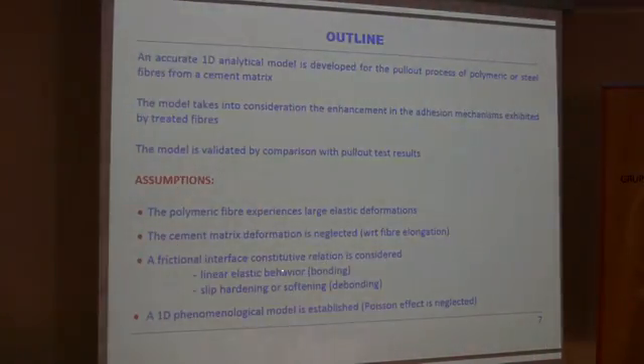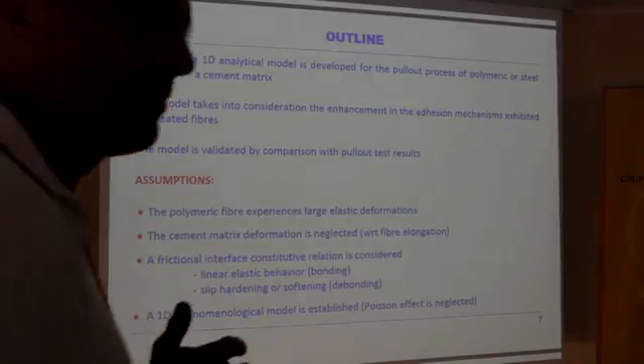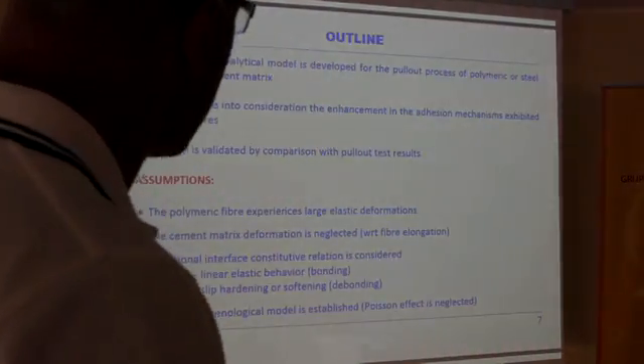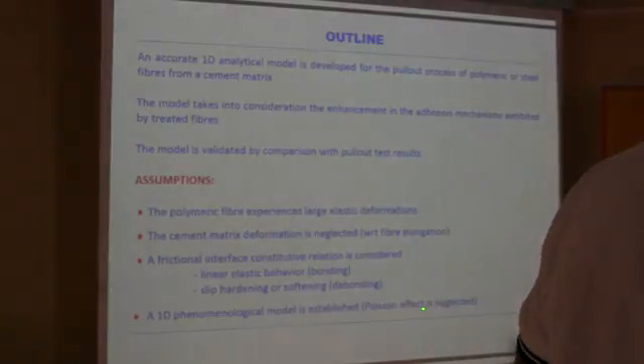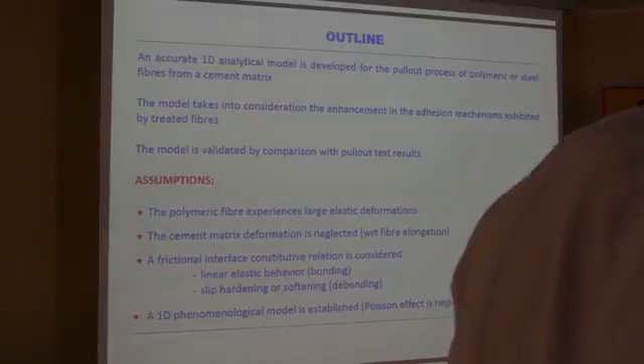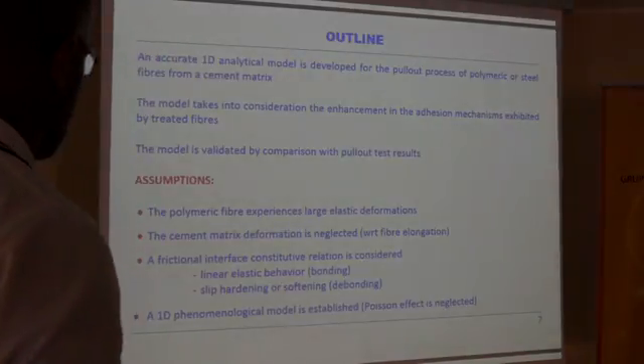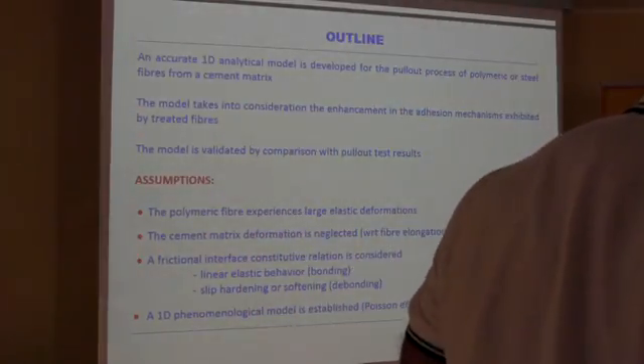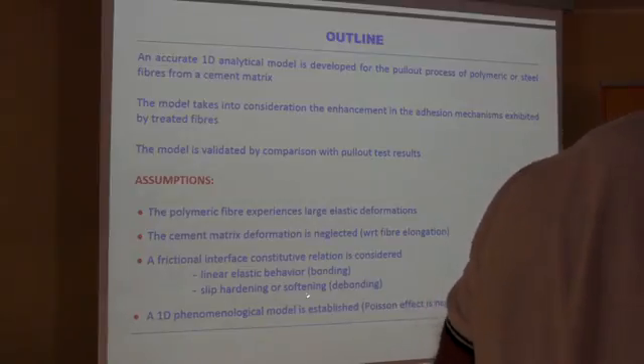This model displays an initial linear elastic behavior between the shear stress and the slip distance, and further a slip hardening or softening behavior in the debonding stage, depending on the kind of fibers. Therefore, we were able to develop a one-dimensional phenomenological model, which of course neglects the Poisson effect, the three-dimensional effect, which is not relevant for this kind of test, for pull-out. The most important feature of the pull-out test of synthetic fiber is due to the slip hardening or softening behavior.